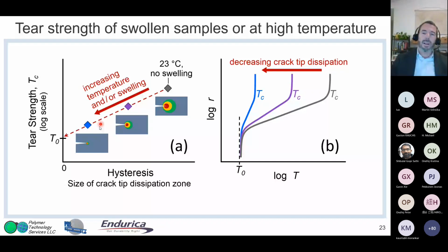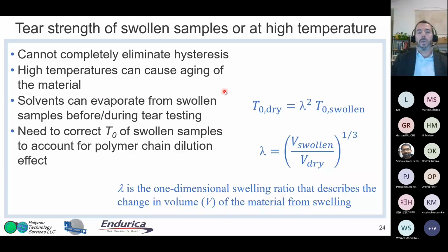This has some problems that you might imagine. First, you can't completely get rid of all dissipation. If you go to high temperatures, when I mentioned 120 C in the last slide, if you're thinking about natural rubber, that makes people nervous. Natural rubber starts to degrade pretty readily above 100 C. If you're using solvents and doing swelling measurements, the solvent can evaporate during testing. And then if you do swelling, you have to correct the T0 because of the swelling.